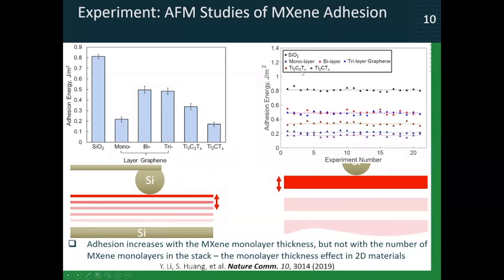Whereas for graphene, here is the monolayer, and then the bilayer, and you see how adhesion energy changes. So for graphene, the change is very significant, whereas for MXene, it doesn't matter how many monolayers you stack, the adhesion force doesn't change. And then we started to think about why in graphene we don't observe this behavior, and we came up with